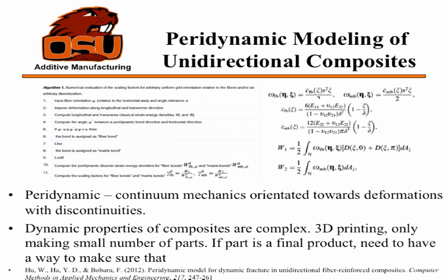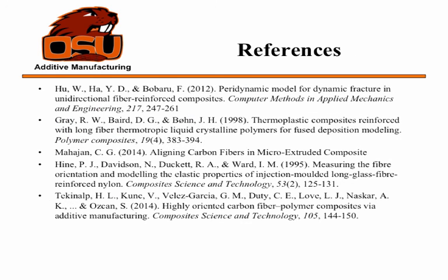And basically, they made this model. They tested out what they thought the different properties were supposed to come out at, and then they did a validation of it, and they found that it was relatively close. The whole reason for this is that dynamic properties of composites are pretty difficult to predict. So if you're doing 3D printing and you're trying to make a structural part with only a small number of samples, you want to make sure that your model is fairly accurate. So this would be something that you could use. Those are some references.